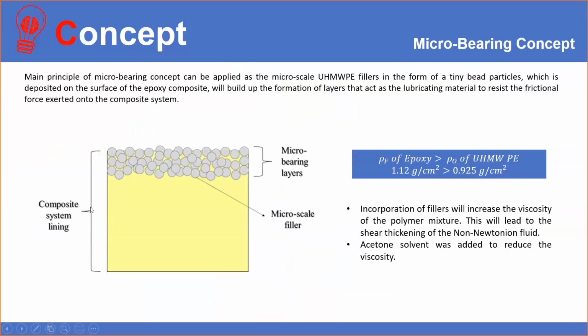So in this study, the main principle of the micro-bearing concept can be applied as the micro-scale ultra-high molecular weight PE filler in the form of tiny bead particles, which is deposited on the surface of the epoxy composite. Due to the difference in density of the epoxy and ultra-high molecular weight PE, it leads to the formation of layers that act as lubricating materials to resist the frictional force exerted onto the composite system.